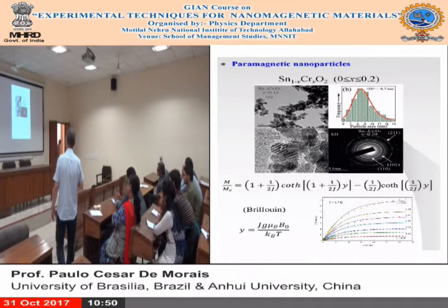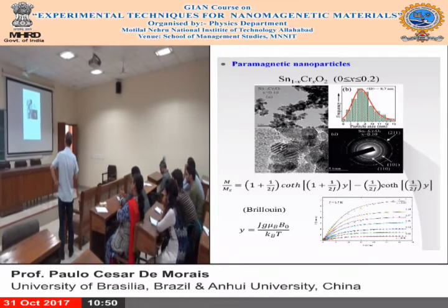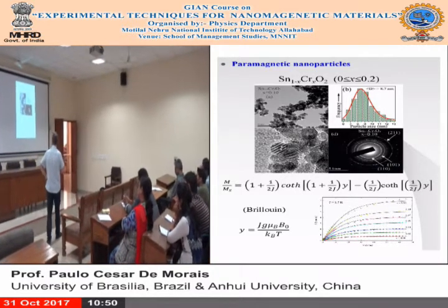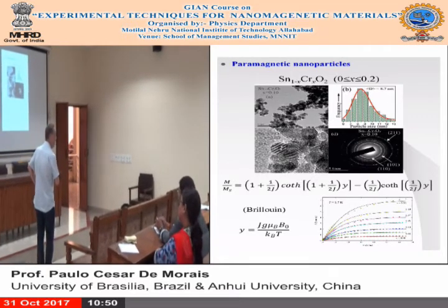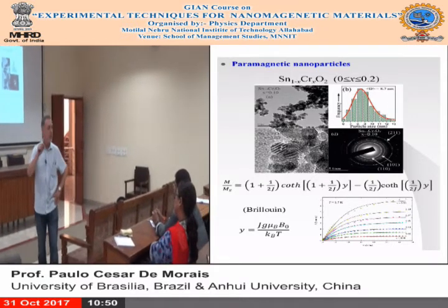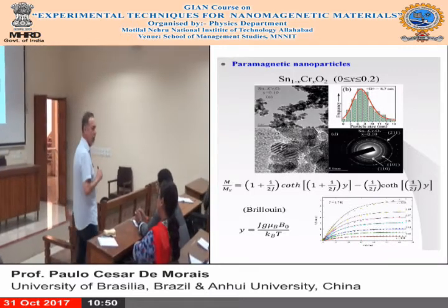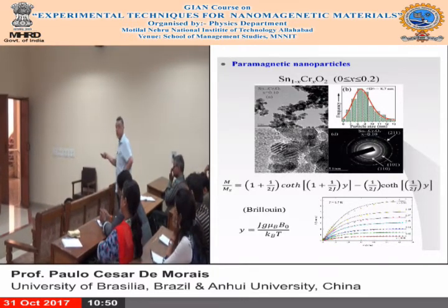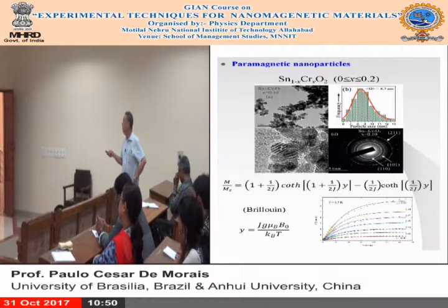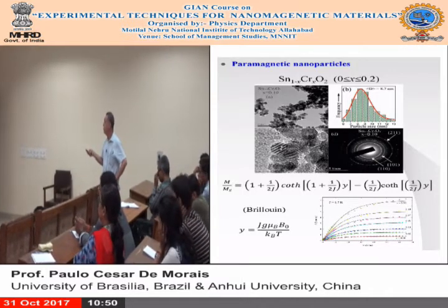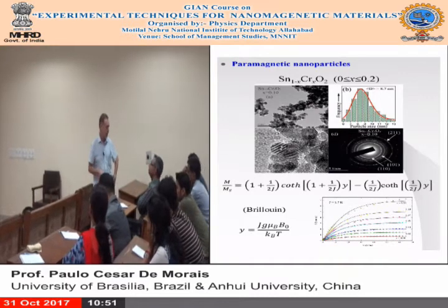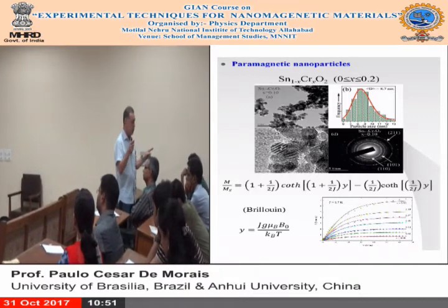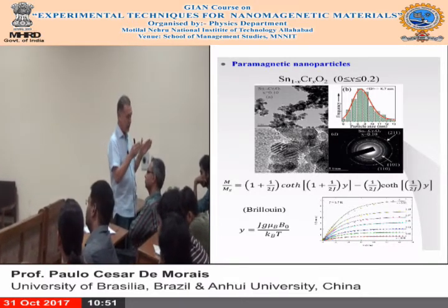So we did the synthesis of those tin oxide nanoparticles. You can see here the TEM and the high resolution, where we can identify the planes and say, okay, the sample we synthesized is exactly tin oxide. It's very important these days to make this sort of characterization. You can also make your particle size distribution. This one, the average was about 9 nanometers, and you can check how wide the distribution is. Make it as narrow as possible.